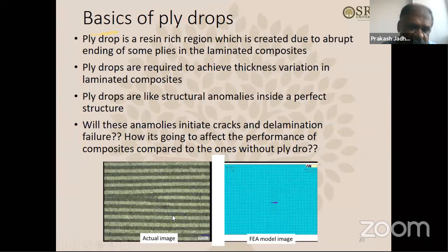So plies are made of basically fibers and resin. When you drop the ply, it creates a space, and in that space a lot of resin accumulates. That is called the resin-rich region, which is created due to the abrupt ending of the plies. And ply drops are required for achieving thickness variation, and they act like a structural anomaly inside a perfect structure.